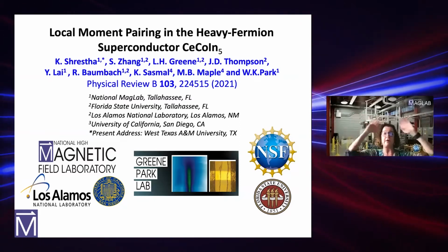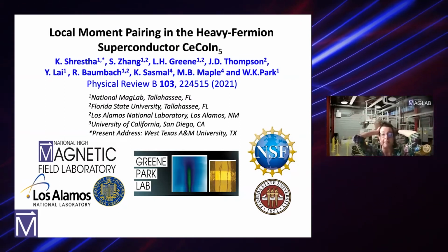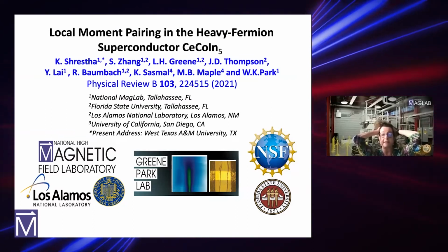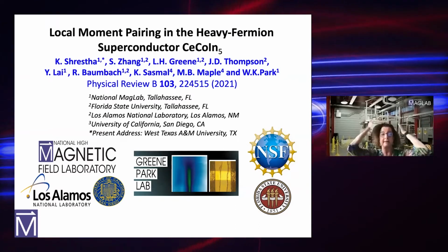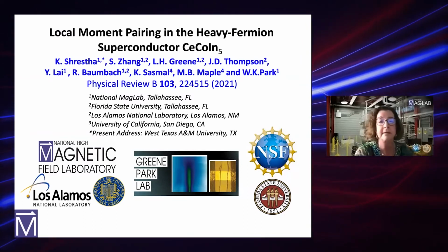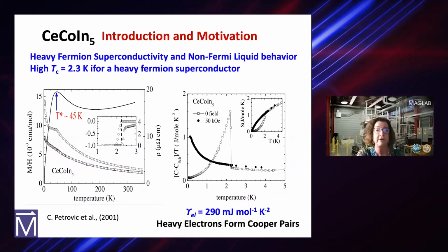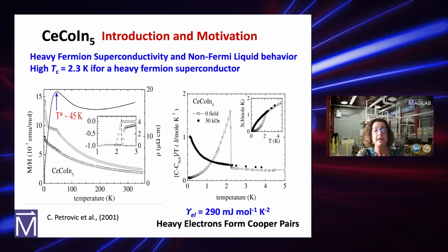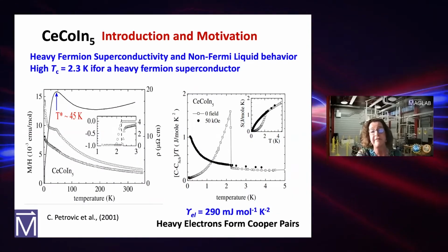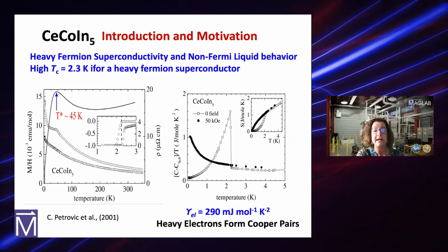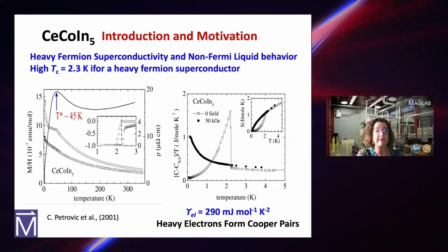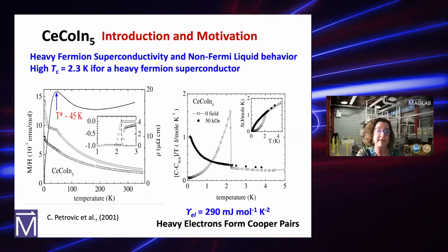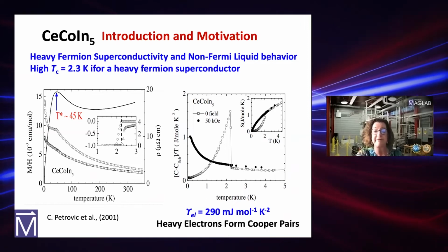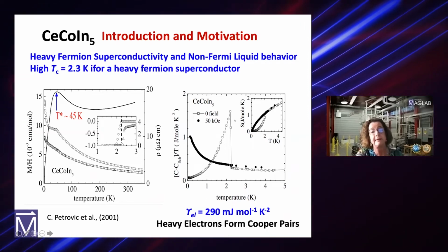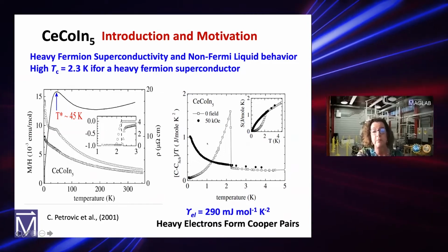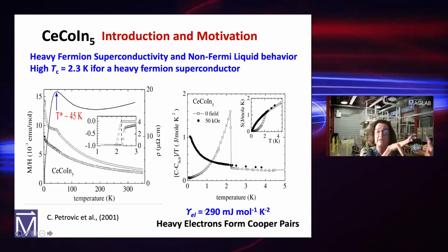So now I'm going to go to something that's a lot more technical. We're doing a big jump, and this is something that's in Physical Review B in 2021, and we're pretty excited about it. The motivation is we've been looking at cerium cobalt indium-5, a heavy fermion superconductor, for many, many years. It has non-Fermi liquid behaviors, as they all do. Tc is 2.3 K, and it has some funny jumps in the specific heat and the susceptibility. And what we do know is that the heavy electrons are the ones that form the Cooper pairs.